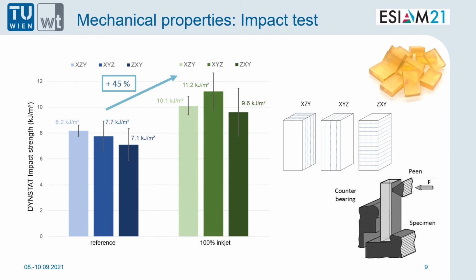This first adaptation of a stereolithography plus inkjet hybrid system was therefore more than successful regarding general feasibility studies. So we can now print small parts from two different materials and even see an effect on the thermomechanical properties. But this system has its weak points. It is barely heatable, therefore we are limited in the materials which can be processed. The ink system does not allow for any post-curing, and of course it is of no real industrial relevance because it is slow and the building platform is very small.